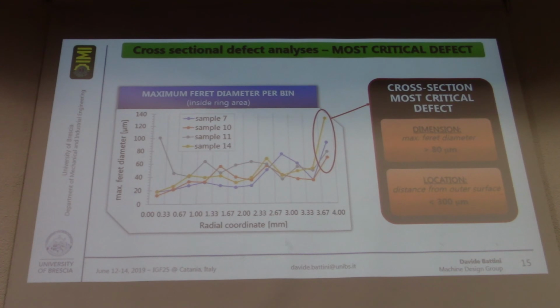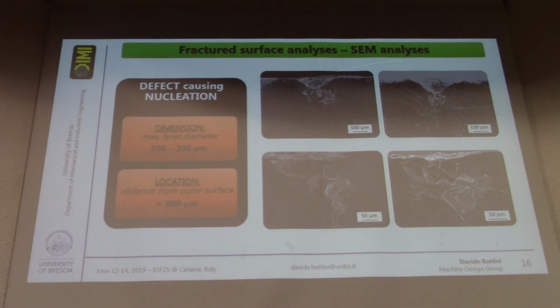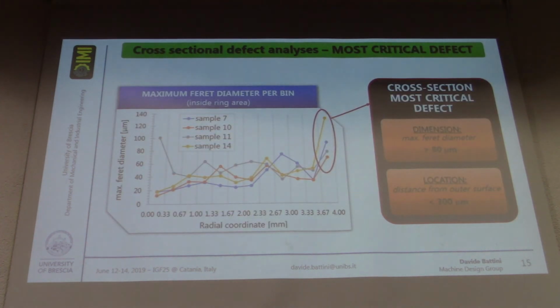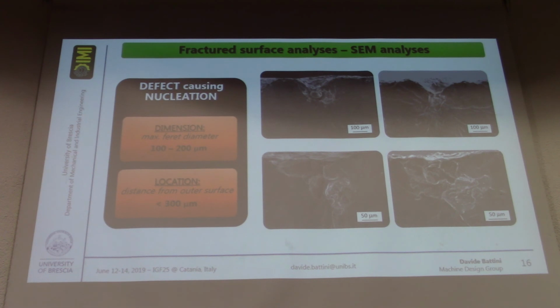Now, this is also interesting since we also took into consideration the maximum Feret diameter to check where the most critical defects were located. And in all the 4 samples we analyzed, the most critical defects, besides this sort of outlier, are in the outer region. Even though we actually are in the axial regime, this was also in good agreement with SEM analysis, which showed on every single fracture specimen that the crack was nucleating on the surface or on the subsurface. And we were really happy since we carried this out without having looked at the SEM, and when we saw that there was a really good agreement, we were pretty happy about it.